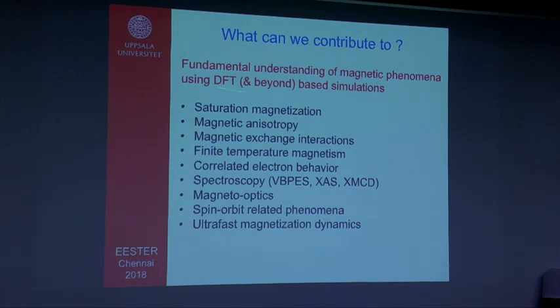So, of course, fundamental understanding of magnetic phenomena, what is happening on a microscopic scale, in the scale of electrons and atoms, we can actually look using our DFT-based simulation, sometimes going beyond DFT. And some of the things that we can actually calculate, I'm going to discuss here. For example, saturation magnetization. This we can calculate, and this can be readily compared with experiment. Until and unless you compare with an experimental value, the experimentalist will not trust you at all. I'm going to show you that this works.